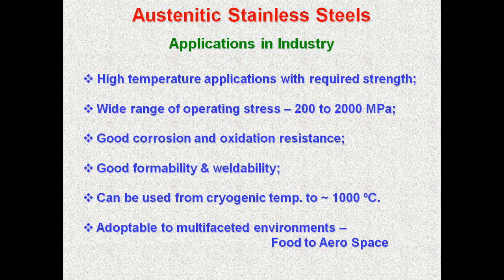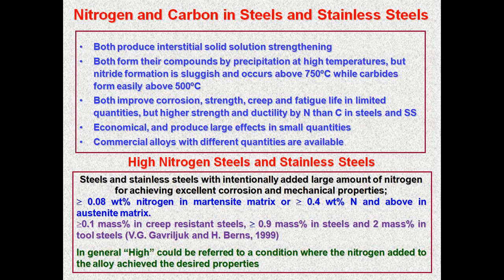Two important elements that I am touching here are nitrogen and carbon, which are in steels and stainless steels. All of us know that both produce interstitial solid solution strengthening. Both form their compounds. But the difference is in the temperature. Easily beyond 450-500 degrees, carbides will form if the carbon is more than 0.027%, that is 0.03%. Solubility limit is very low. Whereas nitrogen has very high solubility and the nitride formation is very sluggish and it occurs above 750 degrees Celsius. So nitrogen has an edge here with respect to precipitation and also gives a much higher temperature application.